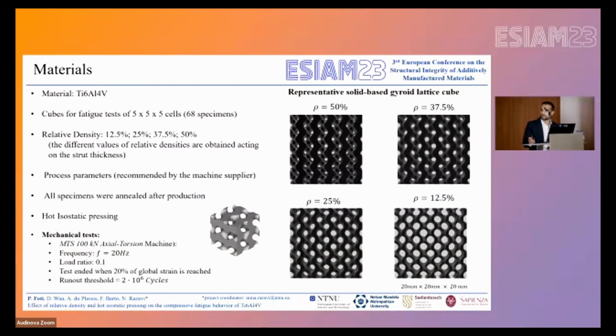The process parameters are the ones suggested by the supplier, so they are optimized for this material. And as I said already, all the specimens were subjected to an annealing post-treatment, while half of the specimens have been subjected also to hot isostatic pressing. The mechanical tests have been performed at a frequency of 20 Hz, with a load ratio of 0.1 in compression, and the test has been ended when 20% of the global strain is reached.